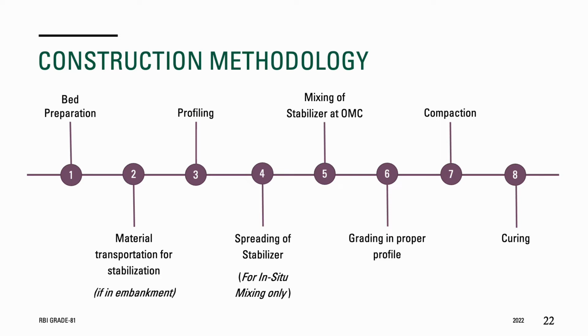After completion of profiling, the optimum dosage of RBI Grade 81 stabilizer is spread on the prepared surface using a spreader. Next, specialized machinery is used to scarify the in-situ soil to the required depth, with simultaneous application and mixing of RBI Grade 81 along with the addition of required moisture content. Upon completion of this process, the mixed layer is then graded as per conventional practices, and the compaction should be completed within 4 hours of mixing.